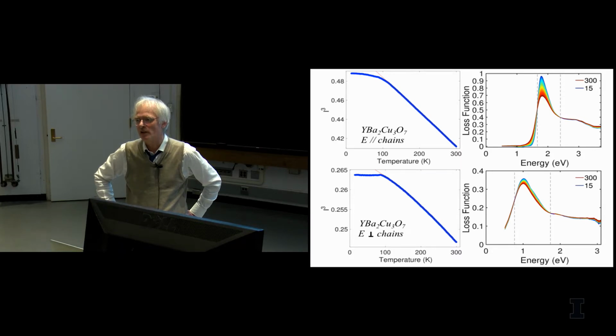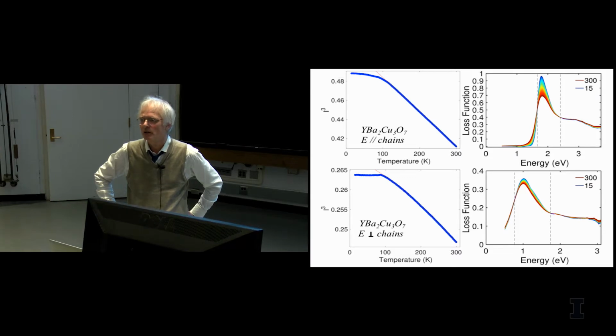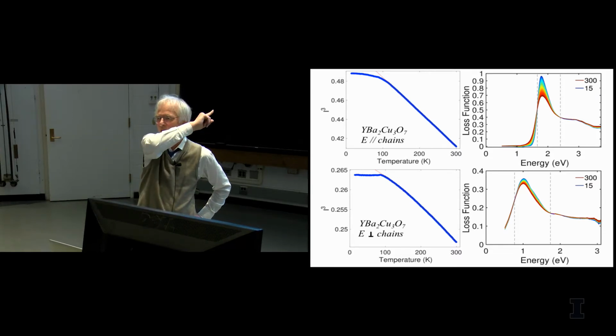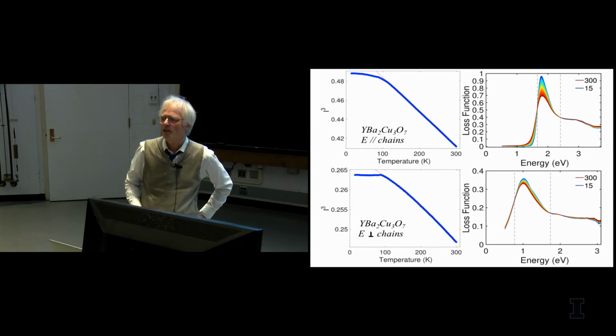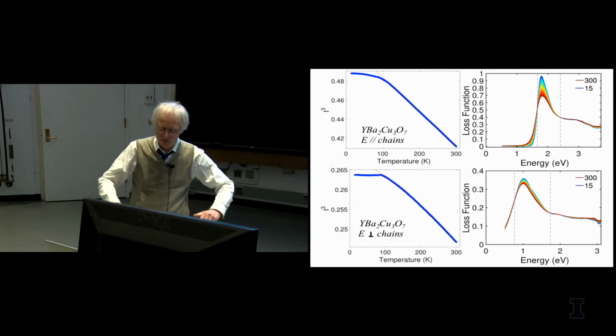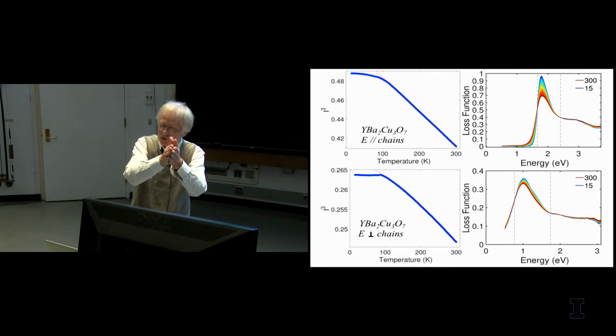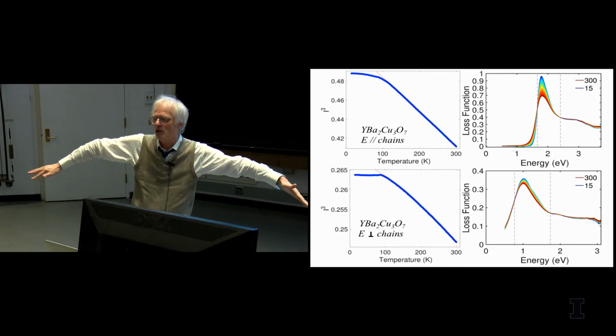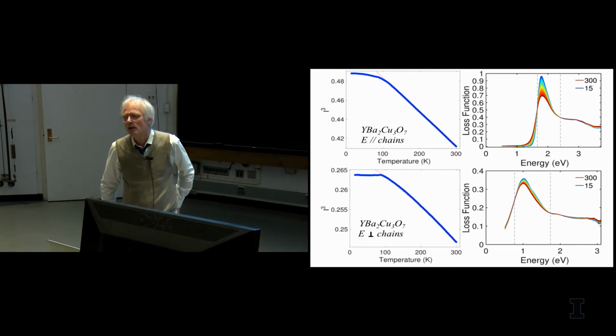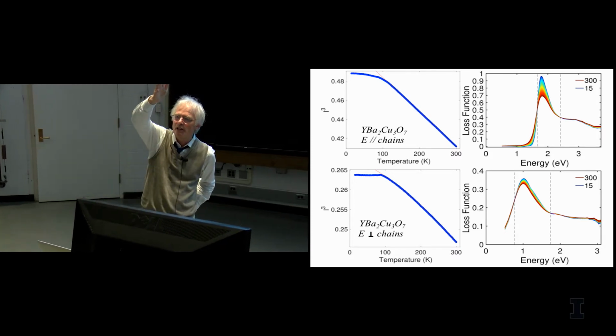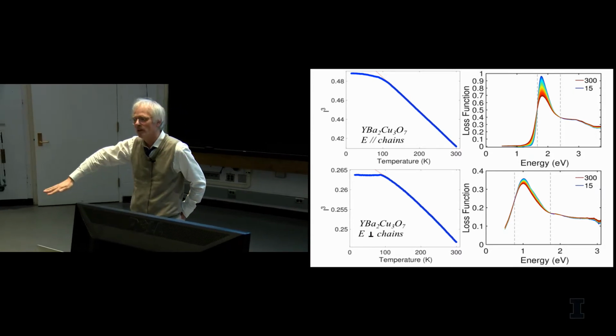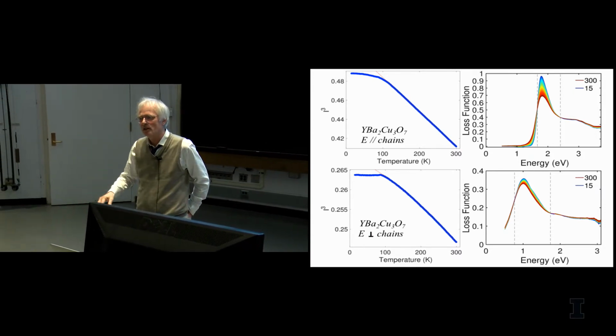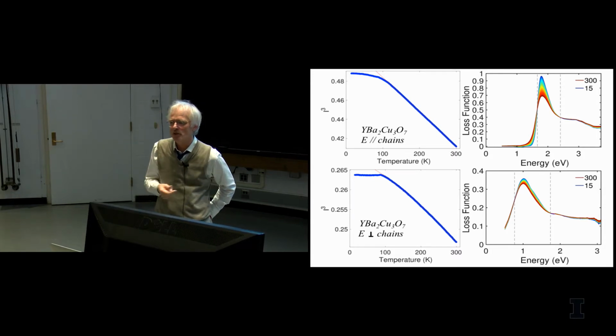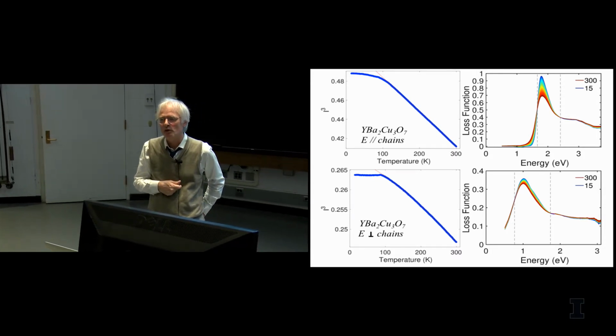I wouldn't necessarily say so. I think this is very nicely consistent with a fluctuation kind of peak. This is actually a paper I didn't talk about, but that we wrote with Tony not so long after this interlayer tunneling business, where you actually see for the somewhat optimally doped and weakly underdoped samples a fluctuation peak around Tc that spreads out over 50 or 60 Kelvin. There also, it seems that this peak just approaches asymptotically 0. It never really makes a kink. Different experiments can give different things there, but it depends also on the compound, I should say.